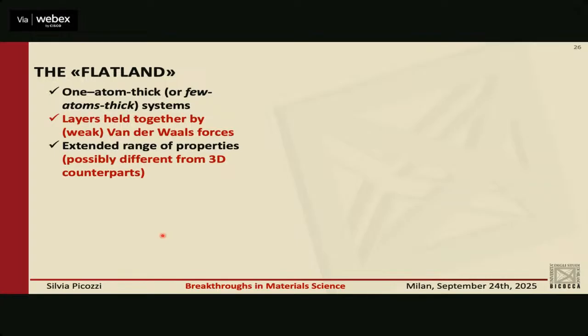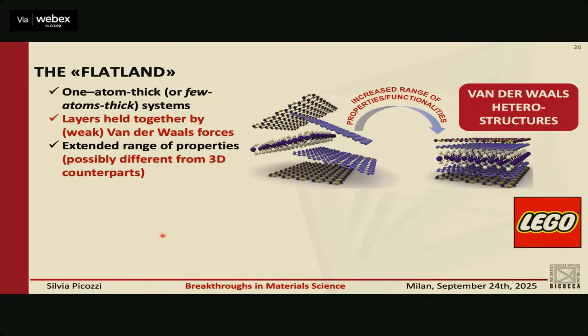And then a few years back, we started to work on 2D materials. So, just a couple of slides to introduce the class of material. These are one or few atom thick systems in which a layer of graphene or molybdenum disulfide is held to the neighboring layer by weak van der Waals forces. And so they have an extended range of properties, but the nice thing is that you can stack them very easily. So people say you can play Lego with these 2D materials. And you can stack them without having to bother about the lattice matching and interdiffusion that, of course, people have to take into account when they work with inorganic or 3D material.